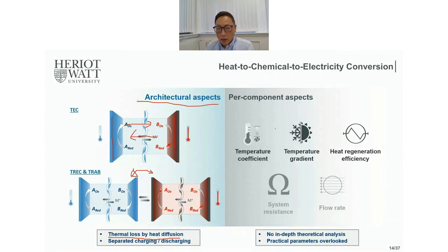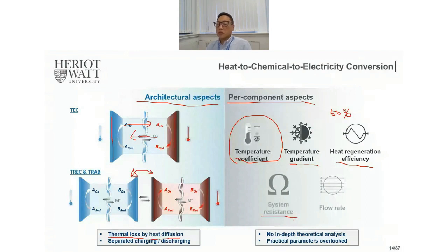And per component aspect, all these studies in the previous slide, they have a focus on the temperature coefficient design to make the high Seebeck coefficients or thermogalvanic coefficient for their redox couples. And temperature gradient, that's fine. And also regeneration efficiency. They also spend some time to make the high efficiency of the heat exchange. But unfortunately, most of them have only 50% or less heat regeneration efficiency because they have used a very poor heat exchanger. None of them, unfortunately, have discussed the system resistance, for example, ohmic resistance or concentration resistance, and the flow rate condition. Unfortunately, there are not many studies that have looked into those two things in depth.